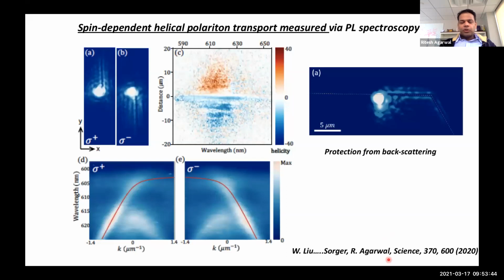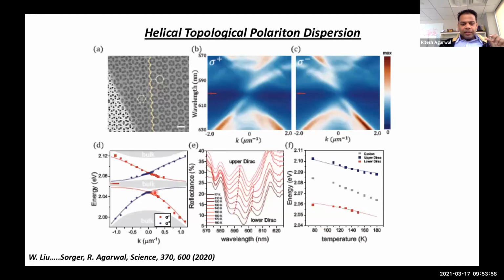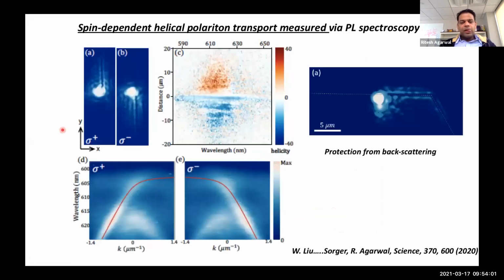If you measure the photoluminescence of these structures, when we excite, these materials emit light. This produces an incoherent mixture of emission. If we create the band gap of this polaritonic mode in the emission regime of this WS2, then right circularly polarized light kicks off the polaritons in one direction, and the left circularly polarized light kicks off the polaritons in the exact opposite direction. We can measure the dispersion of this photo emission. Again, we can see very nicely these bulk modes, and only one particular channel lights up for one circular polarization in the K-space dispersion, and the other lights up the other.